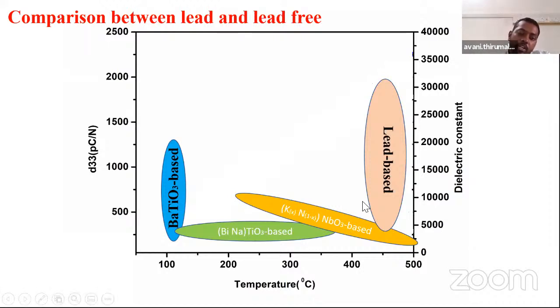If you raise the temperature of a ferroelectric material, this BaTiO3-based lead-free material, the transition temperature is nearly 120 to 125 degrees centigrade. Before that, it will act as a perfect ferroelectric material. After 125 to 130, it will act as a paraelectric material. It won't have any distortion of the crystal structure. If any distortion of the crystal structure is there, it will give some electrical energy and the perfect ferroelectric properties. Otherwise, it can't give perfect ferroelectric behavior.